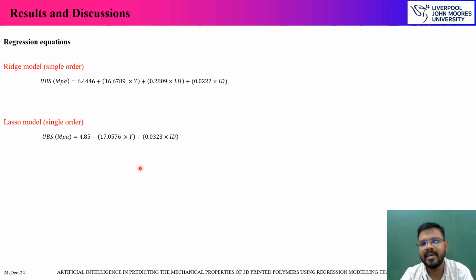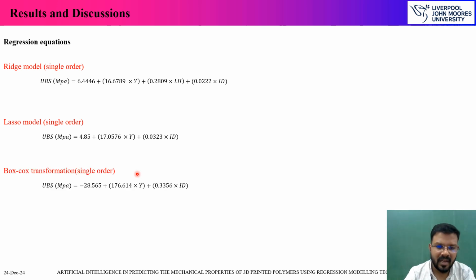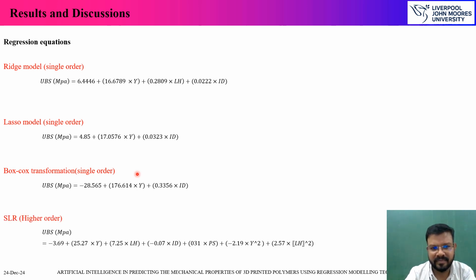The reason for that is the coefficient for those influencing factors is 0. So anything multiplied with 0 is 0. So that's the reason why we don't get to see the other two factors here. We see only 2 out of the 4. And this is the reason why we get to see the skewness towards the left, which is clearly the over predicting model. Now in Box-Cox transformation, this is the equation what we get here with the optimal lambda value and also the higher order polynomial equation.